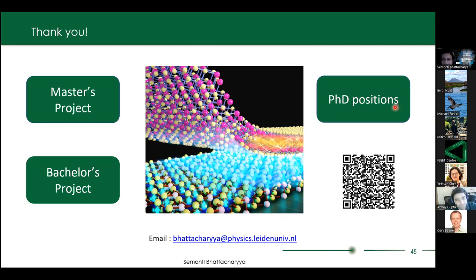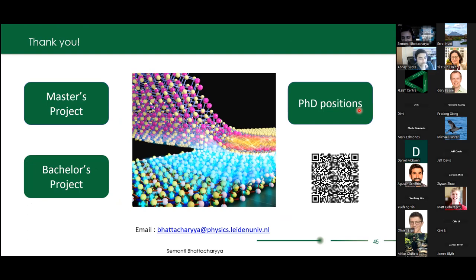Question: How was the graphene structure made — epitaxial growth? Answer: This graphene was CVD-grown graphene — a large-area wet transfer. We actually bought this graphene directly from Graphene Supermarket; it was already transferred on silicon oxide. One small detail: it is actually graphene on a thin layer of hexagonal boron nitride. Interestingly, the hexagonal boron nitride doesn't have any impact on the phonon scattering — we think because it is only one monolayer thick and the silicon oxide completely dominates the remote optical phonon scattering.